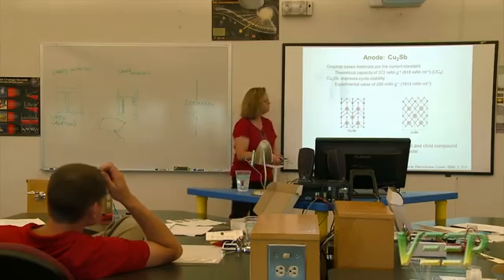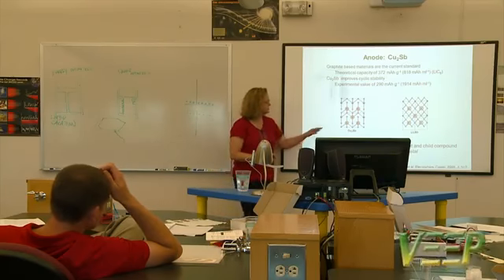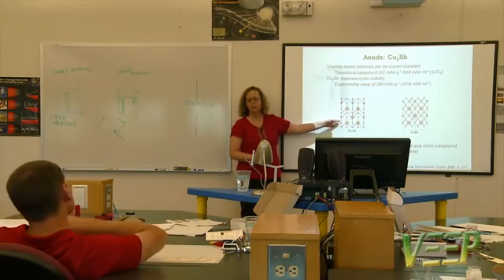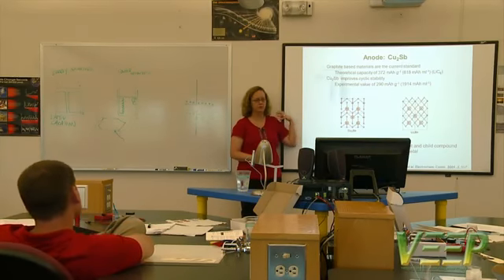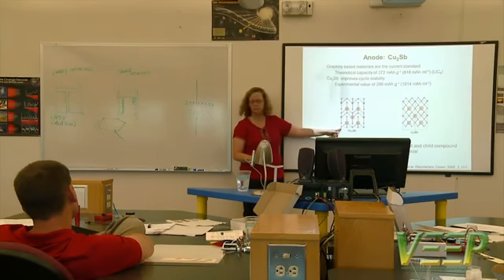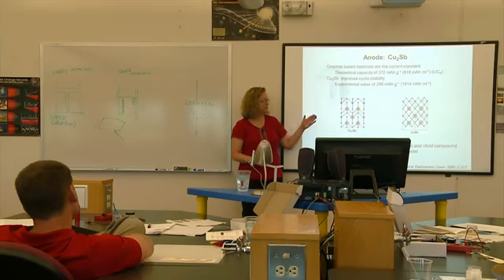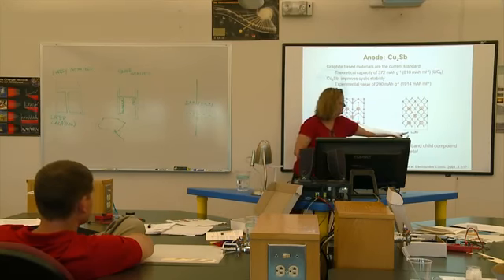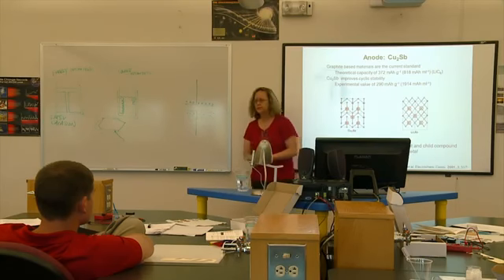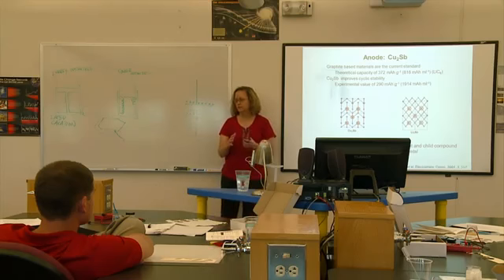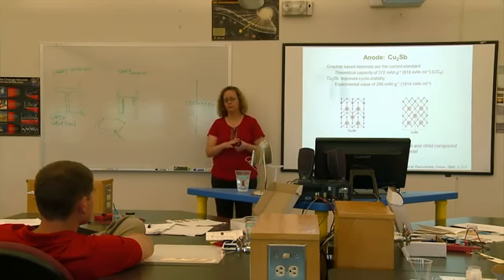Now, the way this compound works is you start with copper antimonide, and this is how the kinds of chemists in my field look at structures. We pretend the atoms are spheres, and in this case, the antimony is gray and the copper is blue. When you charge it, you go through 2 intermediate phases, and you end up at Li3Sb, where now the light blue is the lithium, and again, the dark gray is the antimony. Most of these kinds of compounds have enormous volume expansions, and so they pulverize so fast that you can't really use them. There are companies now trying to use silicon instead of carbon, and it's a similar kind of idea.